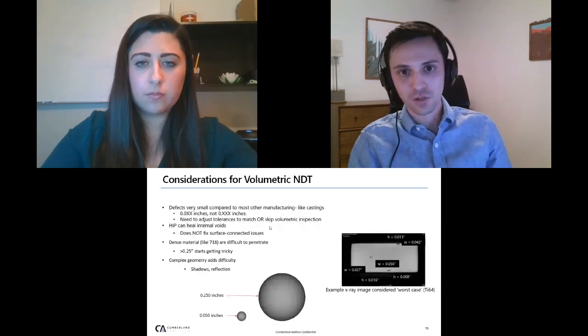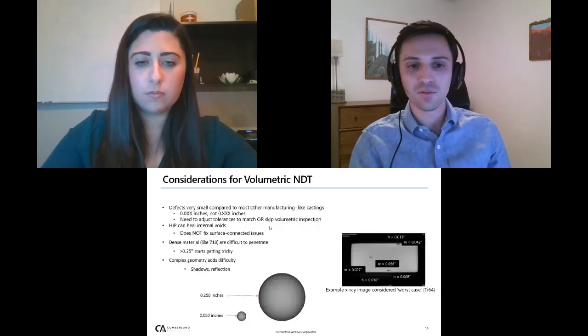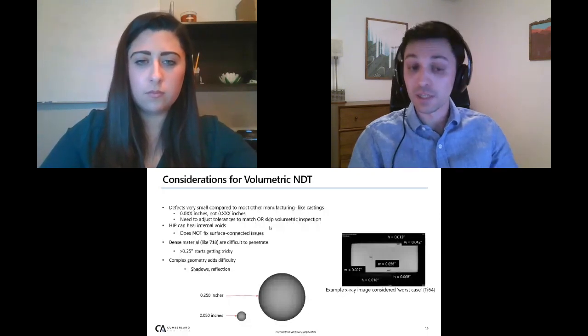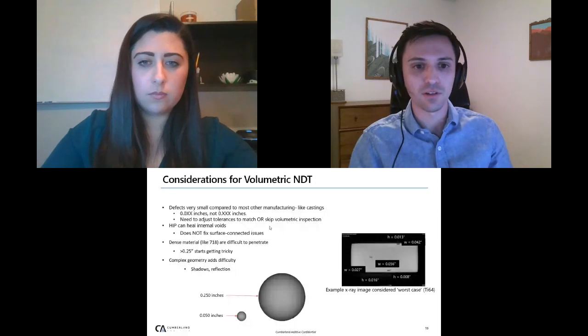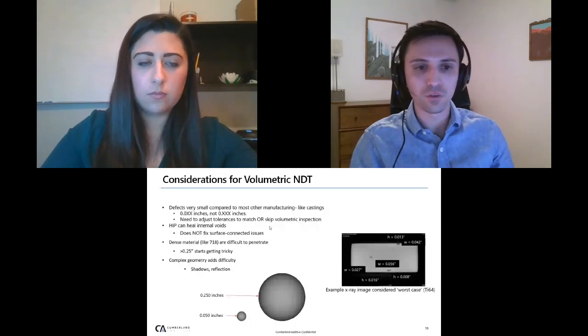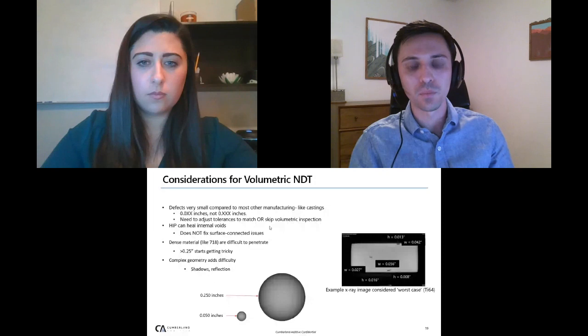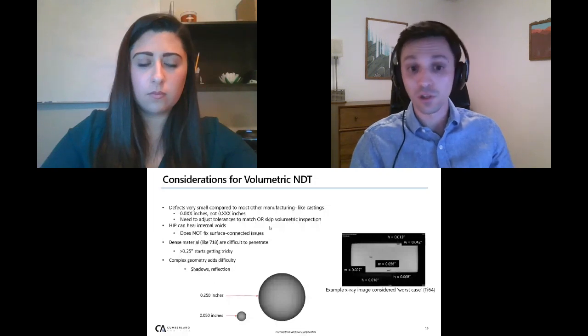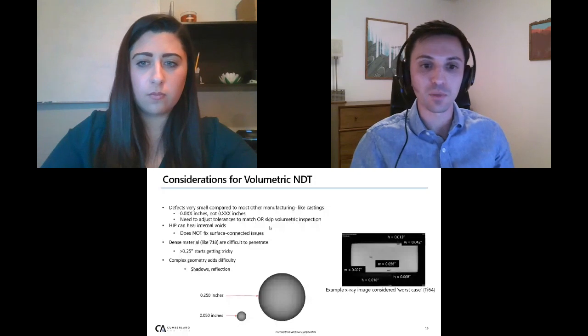Another consideration with volumetric NDT is that if the wall thickness is greater than about 1/4 inch with 718, something fairly dense like 718, it gets really hard to see through that thick of a wall. And then also complex geometry that AM does a really good job with can also be hard to CT or X-ray because of shadows and reflecting that can happen.